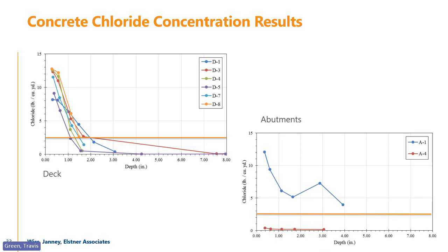So we did the chloride testing, right? Took the cores, did the chloride testing. Here are the results of the deck, and I think the abutments. Decks on the left and abutments are on the right. And what you see here, relative to VDOT's limit, just as a simple 2 to 2.5, is we have very high chloride levels within an inch or 2 of the surface, and then lower levels past that for the deck.